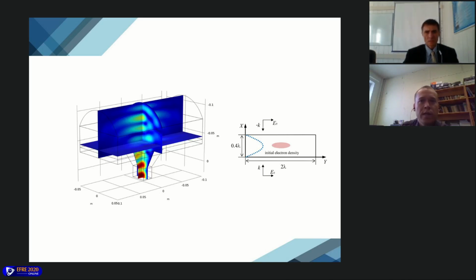It is interesting to study the details of the formation and dynamics of single microwave plasmoids stretching along the electric field. In connection with this, the equations of the microwave discharge were solved numerically for this domain. In order to form one plasmoid in the computational domain, two identical linearly polarized waves from both sides of the two-dimensional rectangular modeling domain were considered, in opposite directions, top and bottom, to form a standing wave. This is the size of the simulation area. At the lateral boundaries of the computational domain, the condition of free passage of the microwave was set.